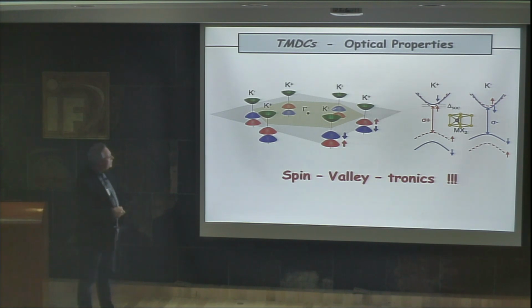So this means that in fact the K point and the K prime point of the Brillouin zone are no more the same. So due to the spin-orbit coupling, you see that, for example, the valence bands are no more degenerate, but you have spin up and spin down for the K minus point, and you have the opposite at the K plus. Okay, and so if you use, for example, circularly polarized light, you can excite a specific spin from the valence band to the conduction band, and if you use the opposite circular light, you can, in fact, excite another type of electron.